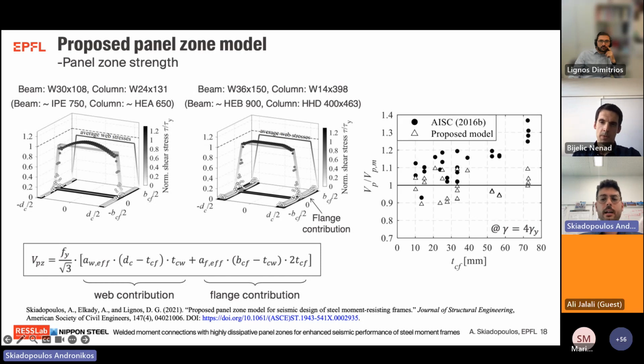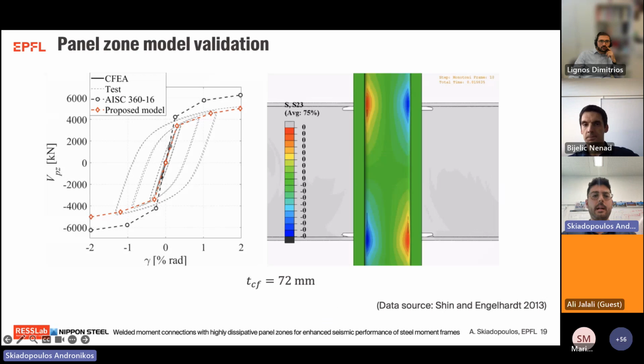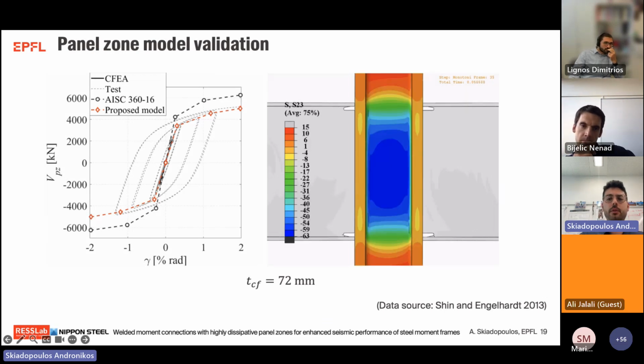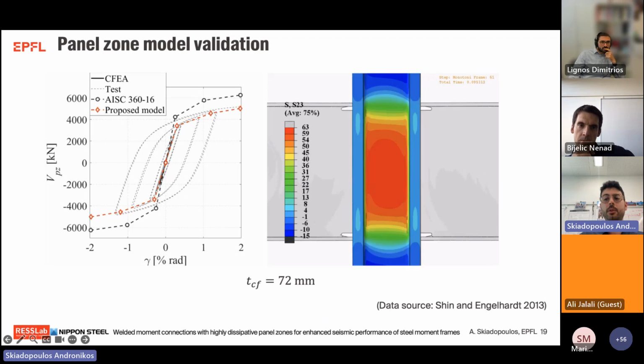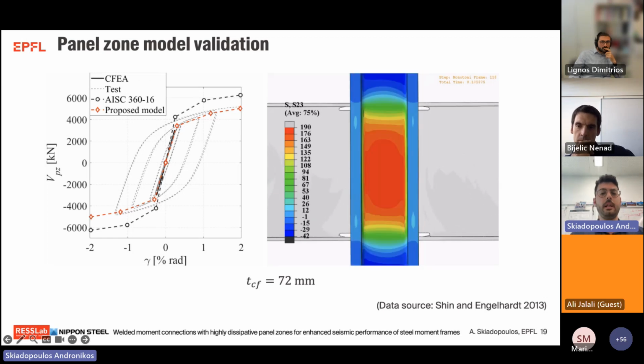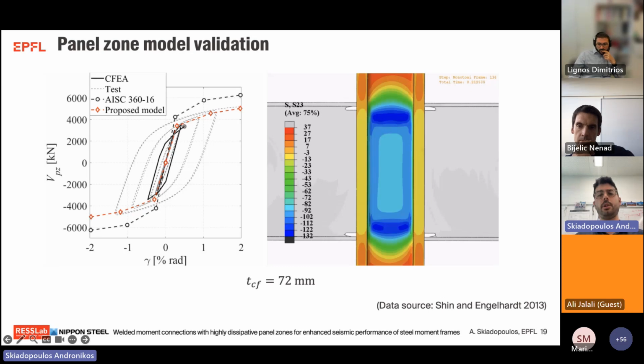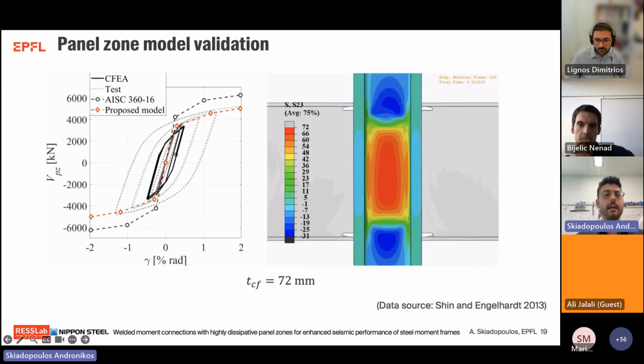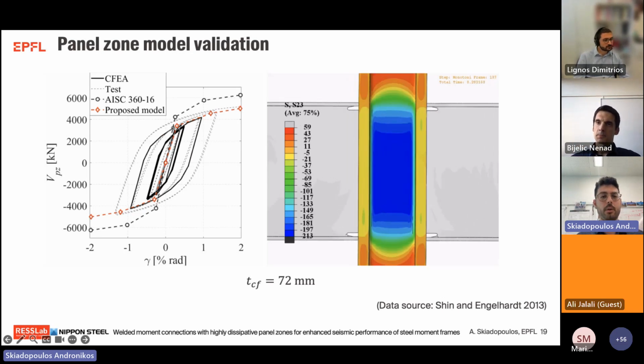Comparisons with available test data reveal that the proposed model increases the accuracy and decreases the variability in predicting the panel zone shear strength at 4 gamma Y, and similarly for other distortions. This is especially critical for thick column flanges of, let's say, 70 millimeters, as highlighted on the right side of the slide. In this video, we see an FE simulation result of an interior subassembly that utilizes very thick column flanges of 72 millimeters. On the left side, we see the shear force versus shear distortion response of the FE and the test data, and superimposed are also the predictions of the American code and the proposed model.